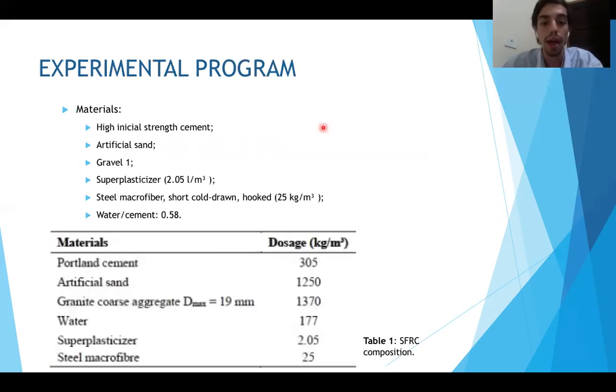We used as materials for molding high initial strength cement, artificial sand, gravel 1, superplasticizer additive, and short cold drawn hooked end steel fibers in a content of 25 kilograms per cubic meter of concrete, and a water cement ratio of 0.58. The dosage of all materials is in accordance with the table shown here.